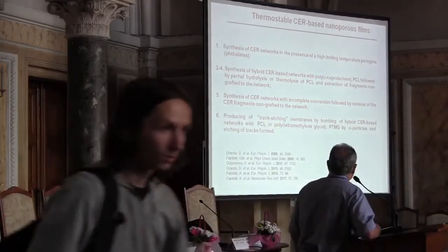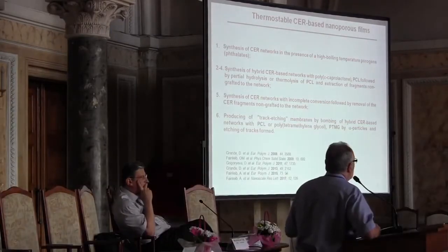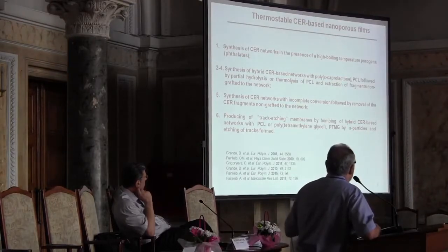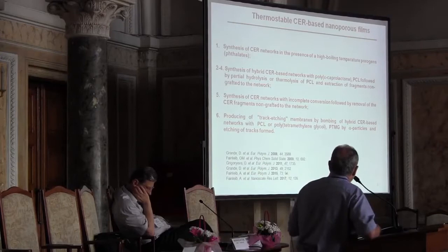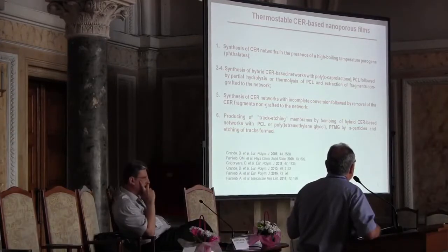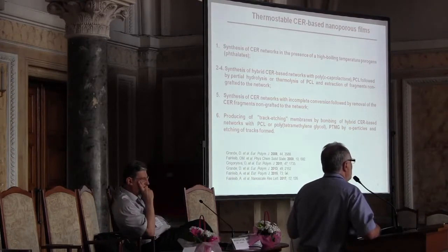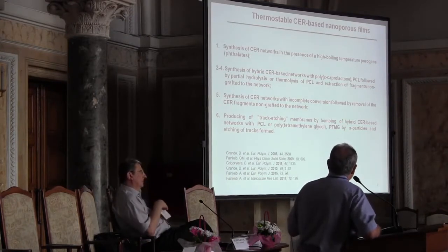For thermostable, cyanate ester-based nanoporous films, we recently developed several methods of generation of nanopores in these films. Number 1 is synthesis of cyanate ester networks in the presence of high boiling temperature porogens, phthalates. It's a high temperature synthesis, and we need high temperature resistant porogens to stay in the system during synthesis.